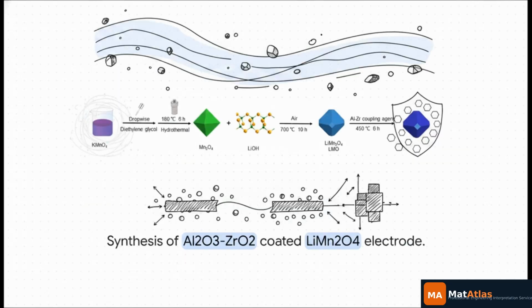But as a materials scientist, I have to be upfront about a core challenge here: electrode degradation. If you drop standard lithium manganese oxide electrodes into these complex brines, the manganese physically dissolves over time. So, to maintain the system's longevity, researchers are engineering incredible nanoscale solutions. By coating these electrodes with an ultra-thin aluminum-zirconium hybrid film, we're talking just 3 nanometers thick, we physically lock the manganese in place. This tiny modification drastically reduces polarization, increases the active sites, and vastly improves cycle stability, pushing the extraction capacity up cycle after cycle.